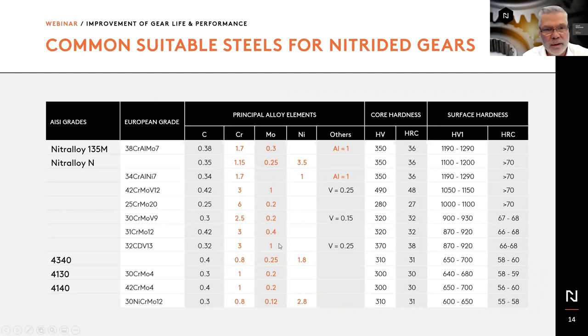So you have two main types of nitralloys that are used on the market. Then you have a whole family of European grades, which are also highly alloyed, well, more alloyed than the everyday 4140 or 4340 you find in North America. One of the ideas here is that if you look at the chromium content, it is much higher. So those are not really low alloy steels and allow for a much harder surface and a much harder case depth. And finally, you have low alloy steels, typically 4140, 4340, and similar, which are everyday steels for the type of gear applications found in North America.